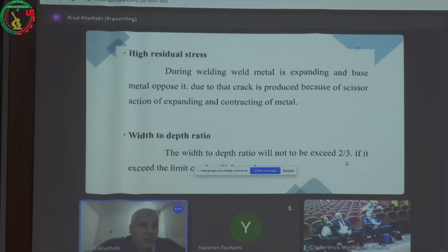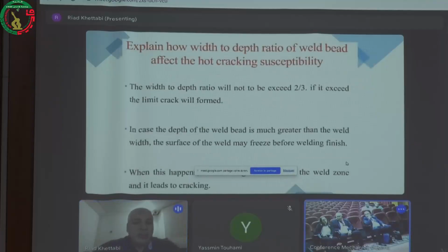Also, we can add the width to depth ratio. The width to depth ratio should not exceed 2/3. If it exceeds this limit, we can have a problem and hot cracking could form. Why? Let us explain. In case the depth of the weld bead is much greater than the weld width, the surface of the weld may freeze before welding finishes and can be fused like a difference in two stages. When this happens, the shrinkage force acts on the weld zone and it leads to cracking easily.